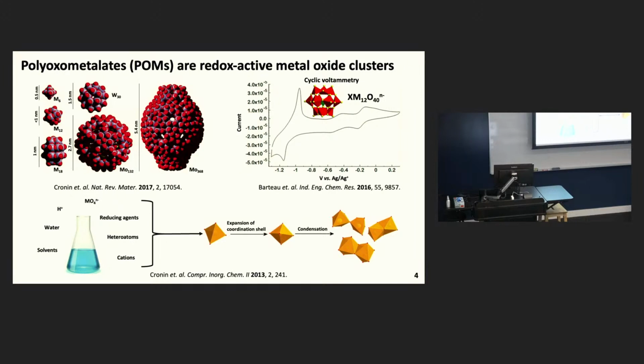So the first system I'd like to tell you about today is polyoxometalates, which are these metal oxide species shown on the left-hand side. They can span a range of sizes all the way from 0.5 nanometer up to about 5 nanometers or even larger in some cases. These are produced in solution using standard techniques, combining these reagents. This results in the formation of a seed, which you can expand the coordination shell of to give you larger clusters such as those shown here.